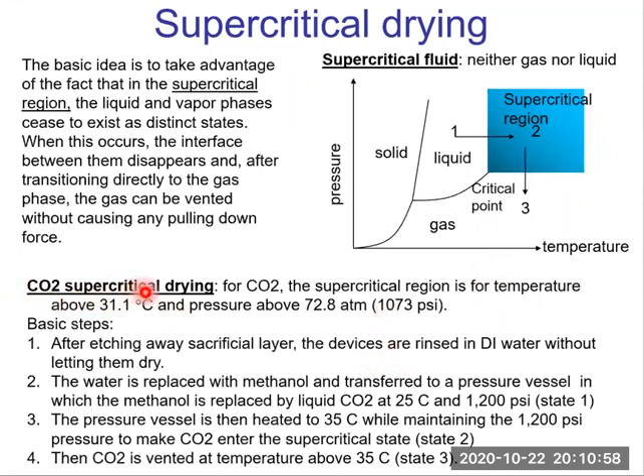CO2 supercritical drying, carbon dioxide supercritical drying. We typically use CO2 as a supercritical medium. That's because for CO2, the supercritical region is for temperature above 31.1 Celsius and pressure above 72.8 atm, atmosphere pressure. This condition can be achieved easily in the lab. So we typically use CO2 for supercritical drying.